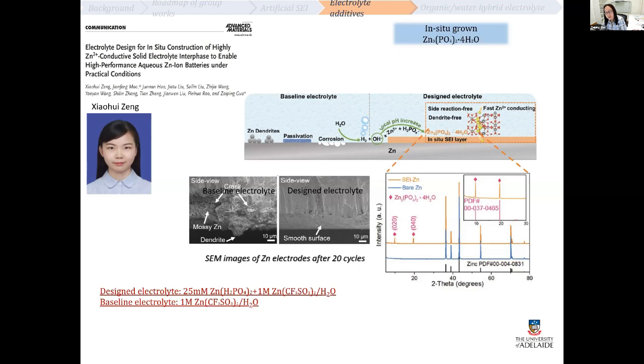However, in the aqueous-based electrolyte, it's hard to form a dense and uniform SEI layer because the reaction products are always porous. They couldn't protect the zinc anode in the following cycling, or it could release a lot of gas, hydrogen gas.